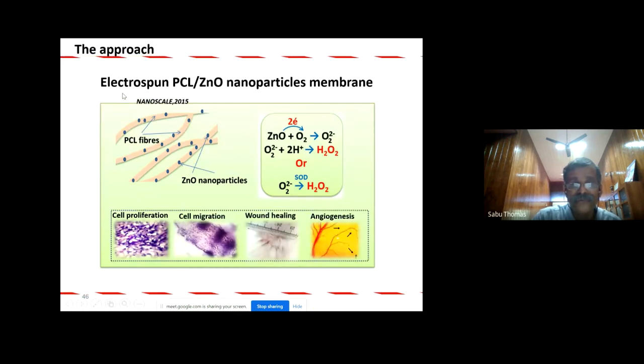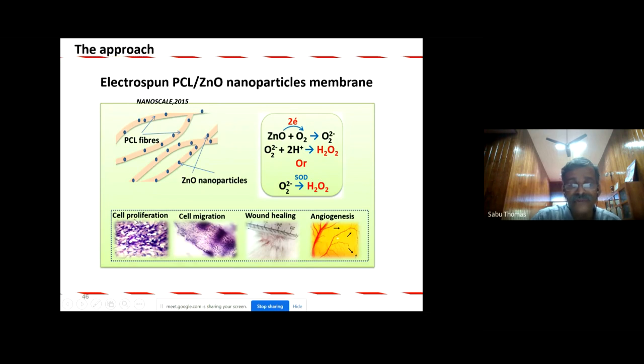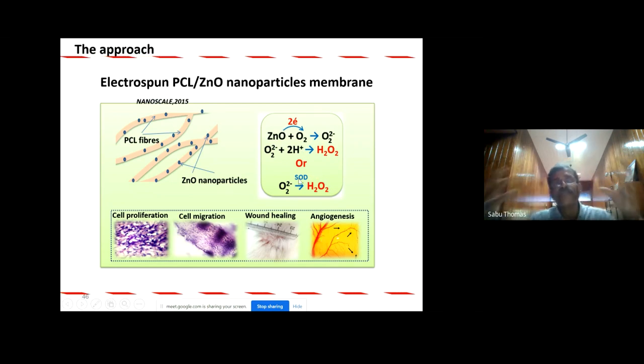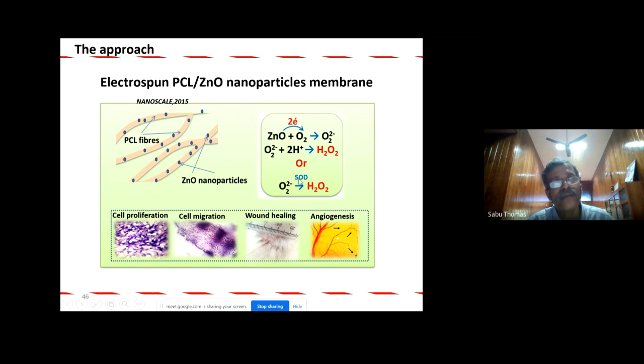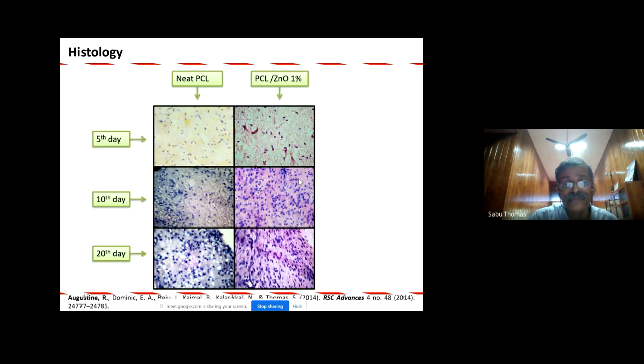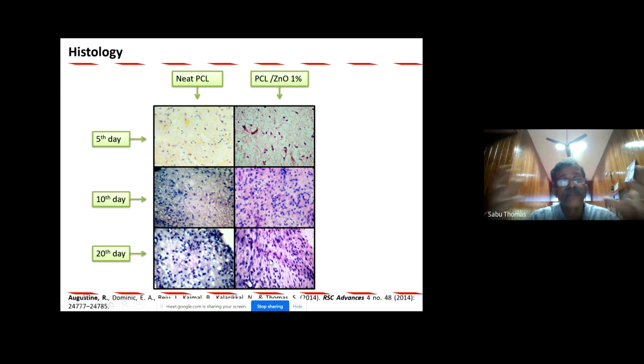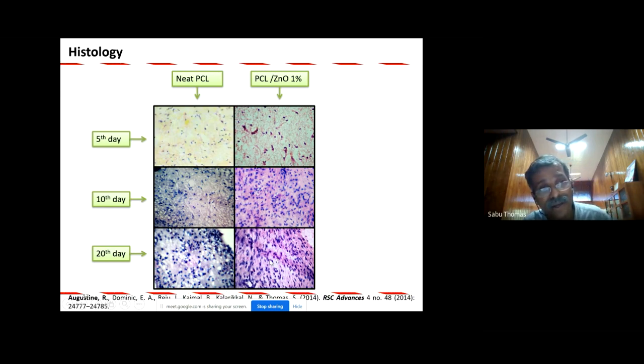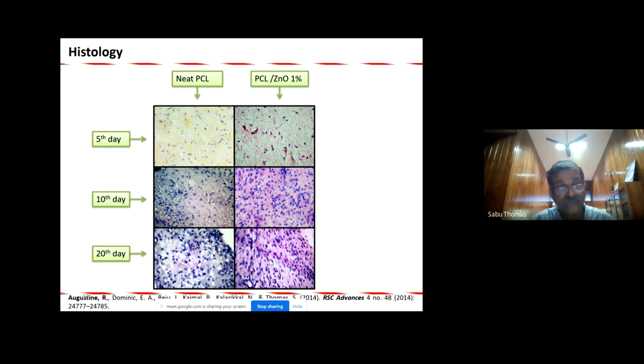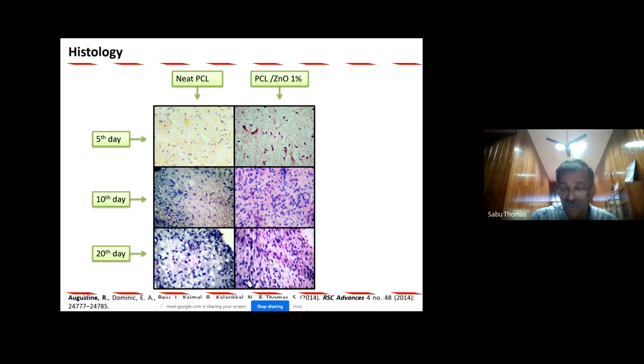This is our PCL and this is zinc oxide. You can see cell proliferation, cell migration, wound healing and angiogenesis taking place. And when you put a little bit of zinc oxide, that gives rise to hydrogen peroxide. Therefore, the wound healing is quite efficient. And you can see the comparison of neat PCL and the PCL with 1% of zinc oxide. 1% of zinc oxide is much better in terms of angiogenesis, fibroblast formation. Look at the histology.